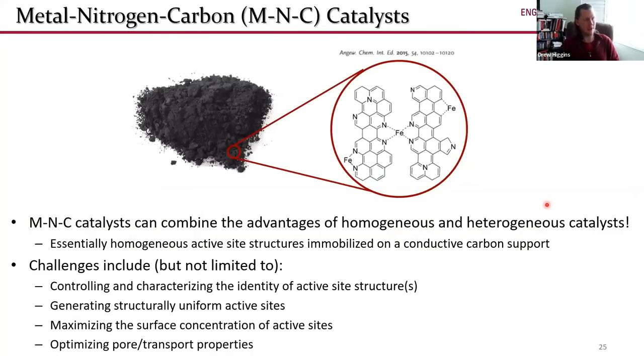And that's a long-winded way of getting to one of the beautiful things about this type of metal nitrogen carbon catalyst: they can combine several of the advantages of homogeneous catalysts and heterogeneous catalysts, where they have active site structures very similar to what a homogeneous catalyst could have, with the potential to have that 100% active site utilization. And all of these are immobilized on a conductive carbon support. So something like graphite: cheap, conductive, get your electrons in, get your electrons out, and then relatively stable. Graphite is a relatively stable material under electrochemical conditions, as long as you don't go to too oxidizing of conditions.